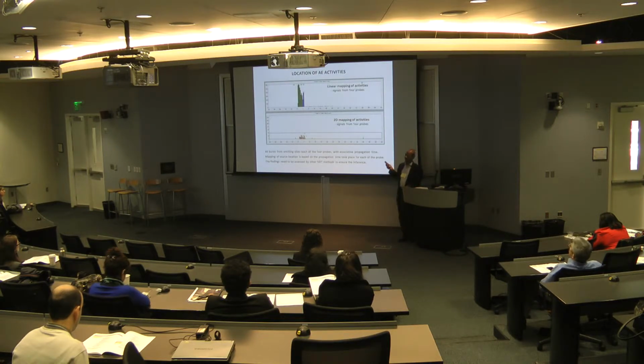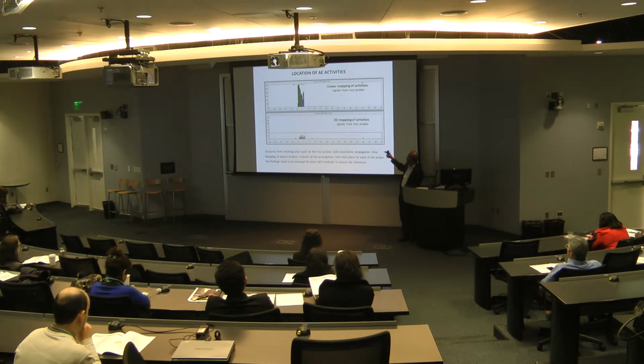This plot gives the location of the source of activity. The top diagram shows the linear plot. It shows the position of the transducers. There are 4 transducers, and we see that transducer number 2 predominantly produces a lot of signal near probe number 2. We have a lot of excitation in that location. Activity is taking place in that space. The bottom diagram shows the 2D plot of the distribution of the signal, which is very close to the suspected area.